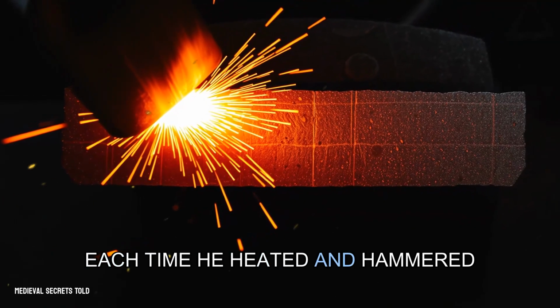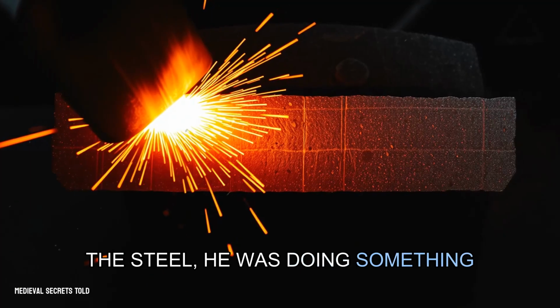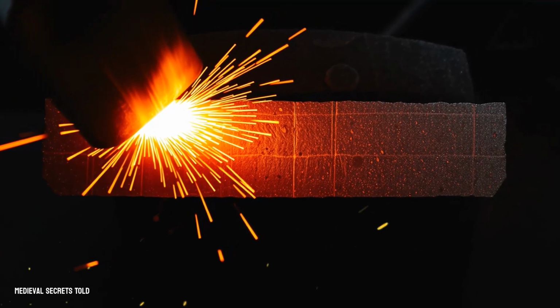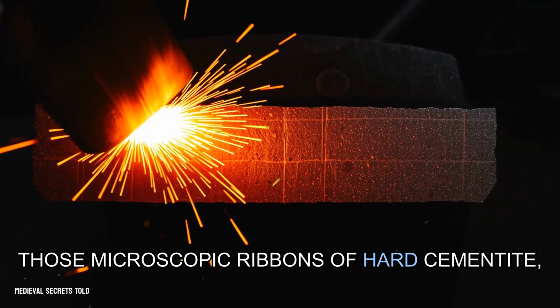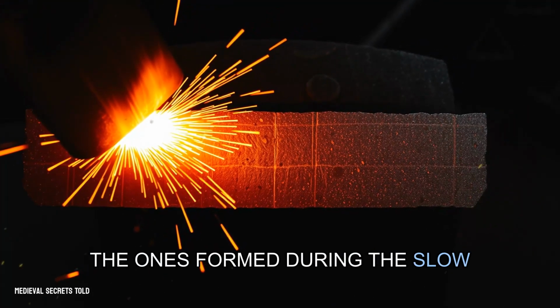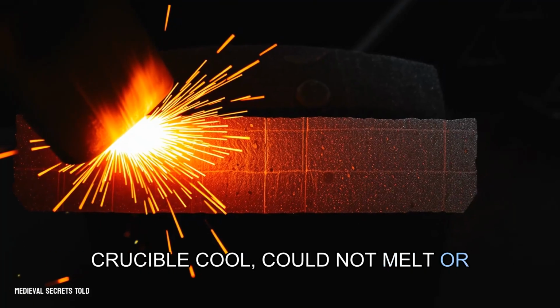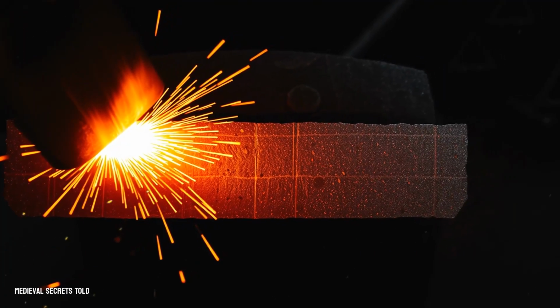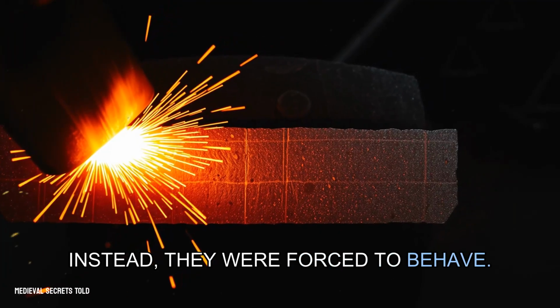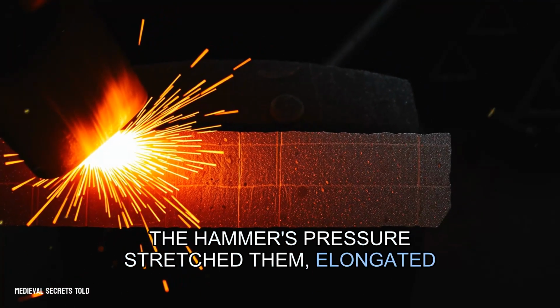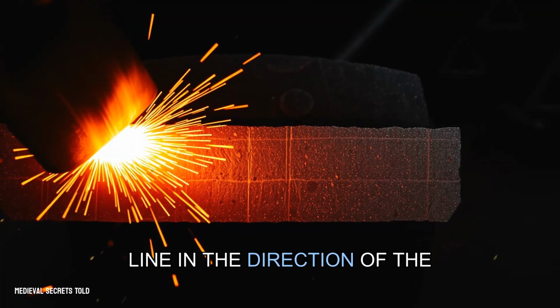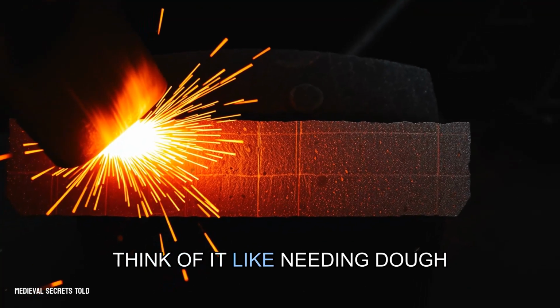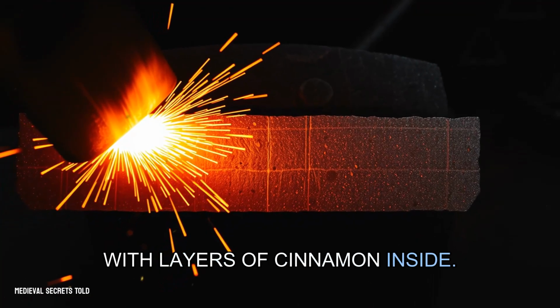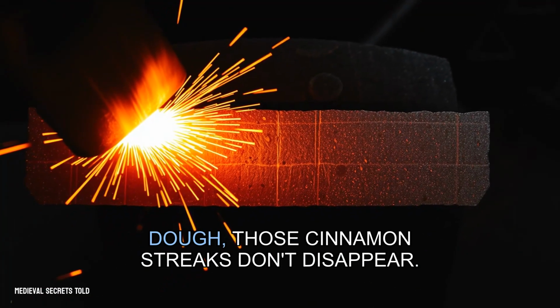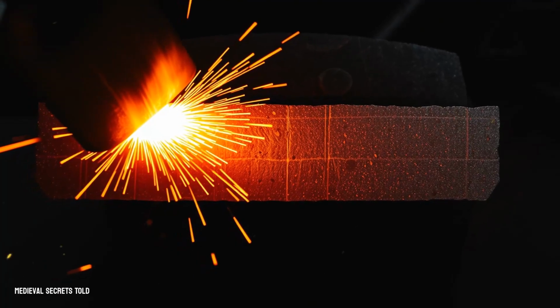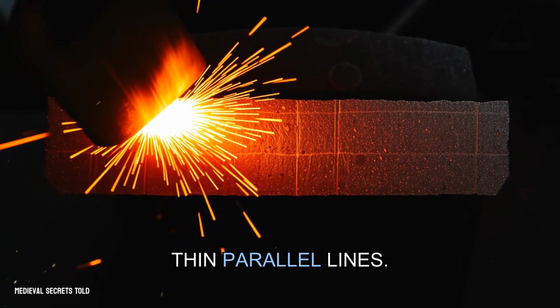Each time he heated and hammered the steel, he was doing something profound to its internal world. Those microscopic ribbons of hard cementite, the ones formed during the slow crucible cool, could not melt or dissolve at these forging temperatures. Instead, they were forced to behave. The hammer's pressure stretched them, elongated them, and caused them to align in the direction of the force. Think of it like kneading dough with layers of cinnamon inside. As you fold and press the dough, those cinnamon streaks don't disappear. They get stretched out into long, thin, parallel lines.